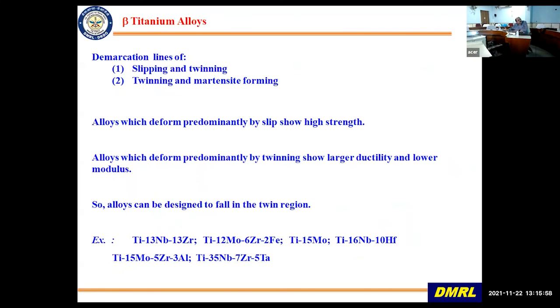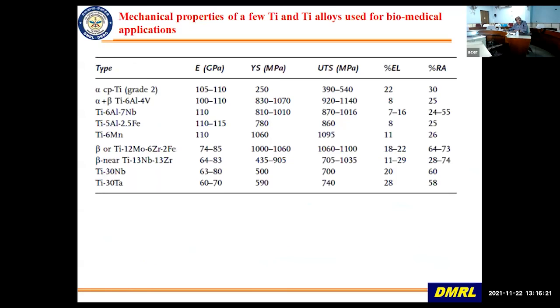So there are ways to design this. The material which twins, that is forms twins, has got lower modulus as compared to material which deforms by slip. So people are aiming at that kind of composition, etc. So there are certain ways to design these alloys. So newer compositions are coming up. Here I am showing you the comparison of the elastic modulus of CP titanium, Ti-6Al-7Nb, which is near Ti-6Al-4V, yield strength, percentage elongation. You can see basically these newer alloys have got much lower modulus.